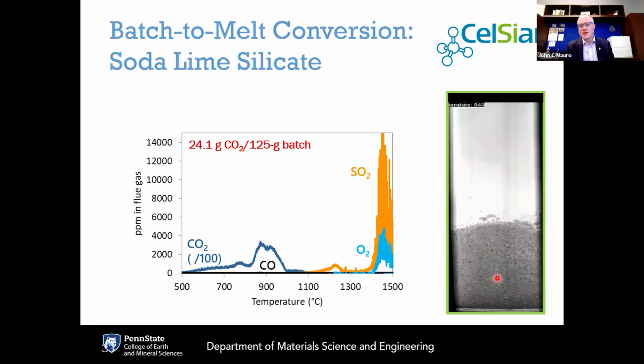So the soda ash, limestone, and quartz sand are being ramped up in temperature. The current temperature in degrees C is shown in the upper left corner of the video. This is at 950 degrees C, and at 950 you can see these batch reactions taking place. The minerals are reacting with each other, forming lower melting temperature eutectics. Gases are being released as the carbonates decompose into oxides.